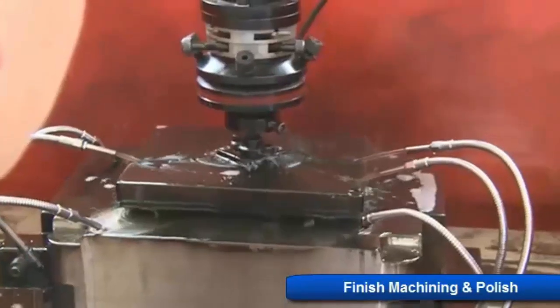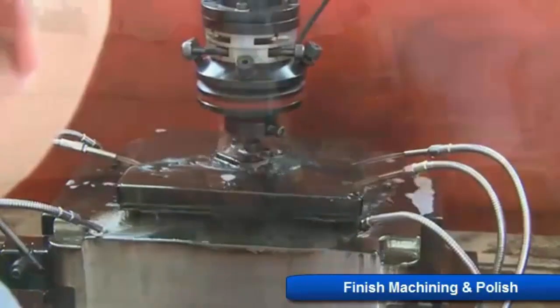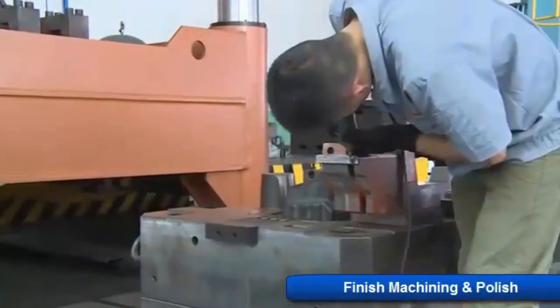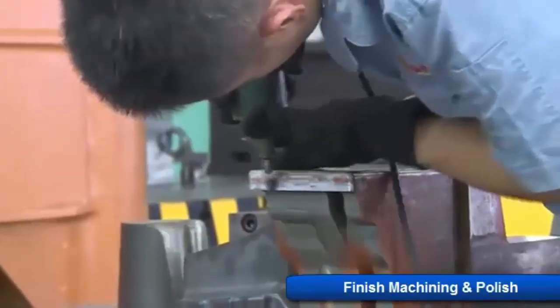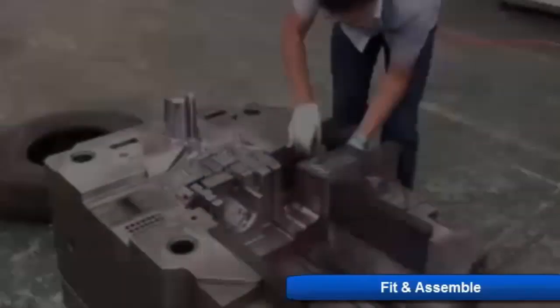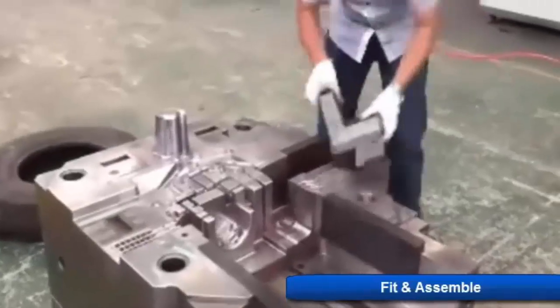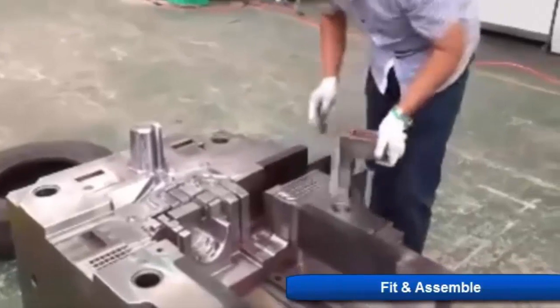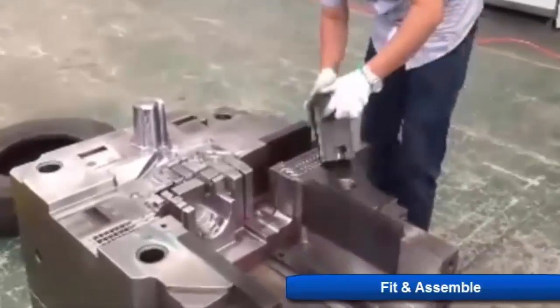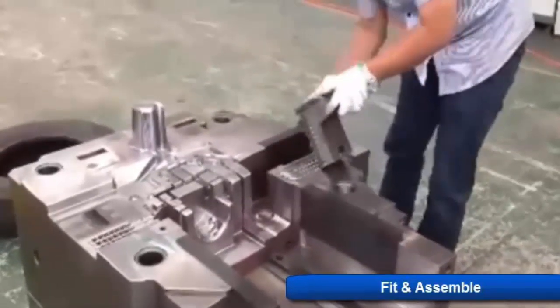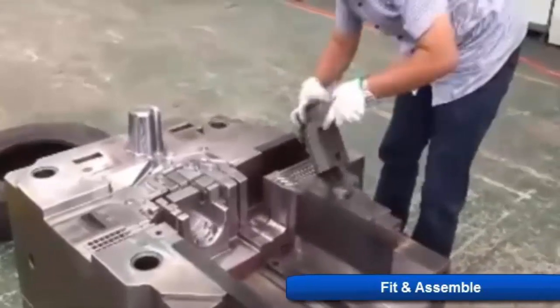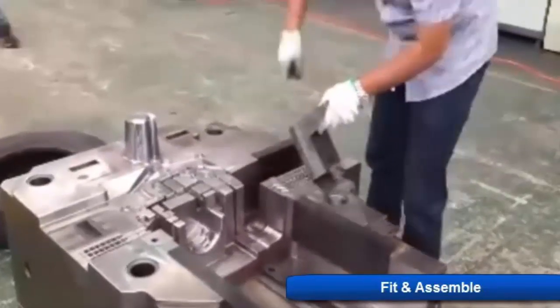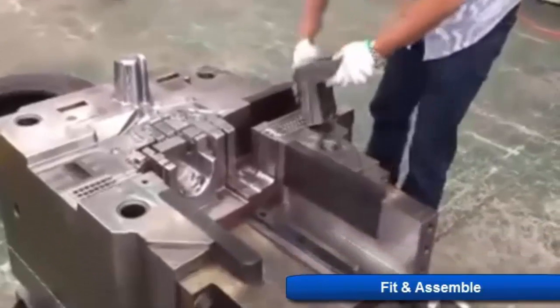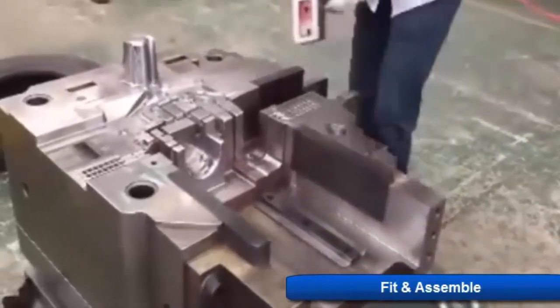Then after it's hardened, we do the finish machining, so you're not taking off anywhere near as much as you were in the rough machining, just those last few thousandths of an inch. Go through polishing, and then the fit and assembly of the die. Even if things are machined to within 1 or 2 or 5 thou of where they're supposed to be theoretically, it always takes a little bit of handwork and nuance to get things to fit together.